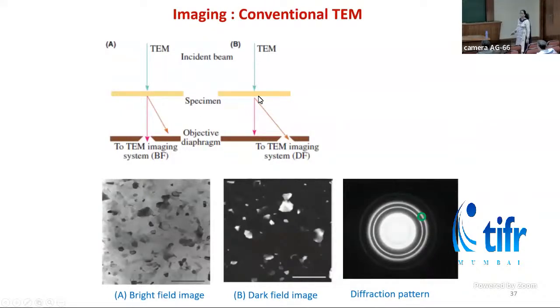Now, how is imaging done using TEM? As I mentioned, the electron beam is transmitted through the specimen, and if we image this direct beam, then we get bright field images. And if we image using the electron beam which is scattered by the specimen, then we get dark field images. So in case of TEM, it is very difficult to interpret the contrast.